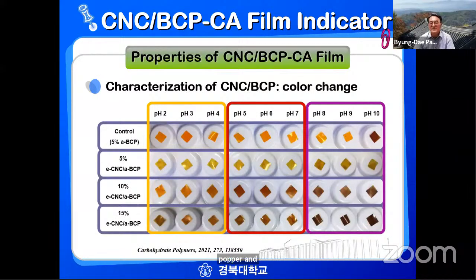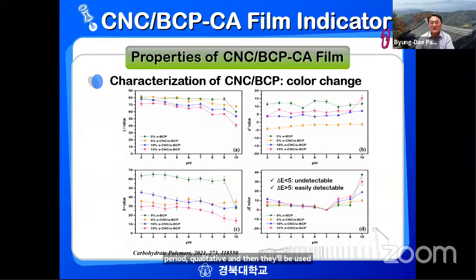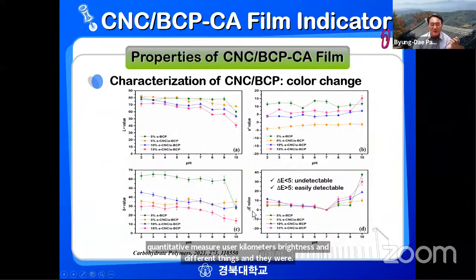And then we made the films and put them in the different solutions from pH 2 to pH 10, with different levels of composite material: 5%, 10% and 15%. As you see, this is the control with activated bromocresol purple only in the cellulose acetate film. But here, 5% shows not much change in colors. This is not good. Then at 10% there is a little bit of change in colors, between pH 7 and 8, and the 15% looks much better. But this kind of evaluation is very qualitative, and then we used a quantitative measure using colorimeters, brightness and different things.